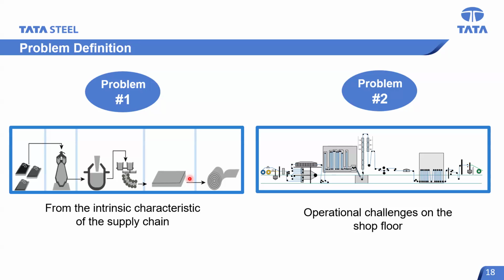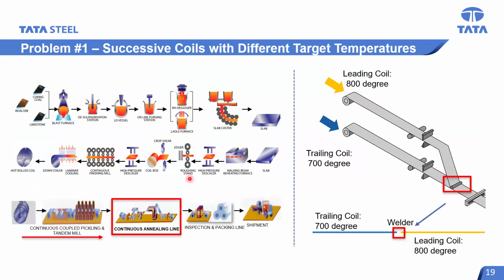The second one is the operational challenges from the shop floor, the plant disturbances. The first one, again, I'm just repeating. We will have a situation where the leading coil has a target temperature of 800 degrees to be met once it passes through the furnace, whereas the trailing coil has a target temperature of 700 degrees, because that is the temperature demanded by that particular grade for it to achieve recrystallization. So we need to manage this transition without over-annealing or under-annealing as they pass through the furnace.